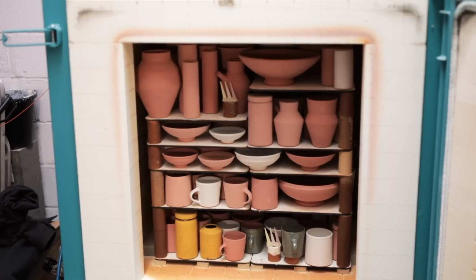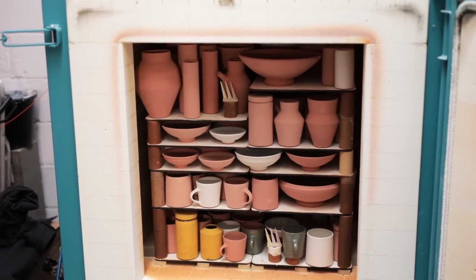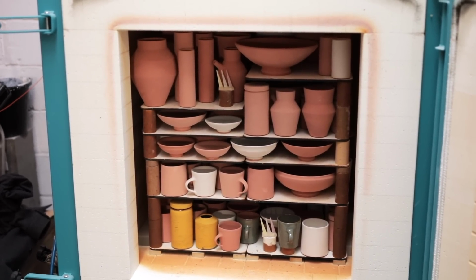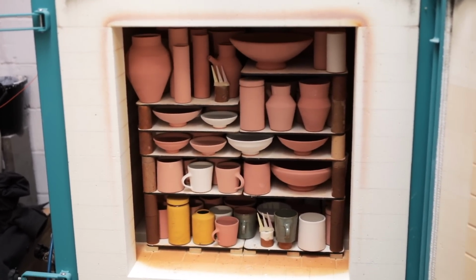I pack this very densely, just like my electric kiln, although in this instance no two pots can touch, as their glazed surfaces turn to molten glass during this firing, and if two pots happen to touch, then they'll be fused together, and I'll have to break them in order to separate them. The kiln is lit with the doors open. This way unignited gas can't fill the chamber up, which is then suddenly ignited, which can cause an explosion. So once all 4 burners are lit, I tightly seal the door and the firing can commence properly.